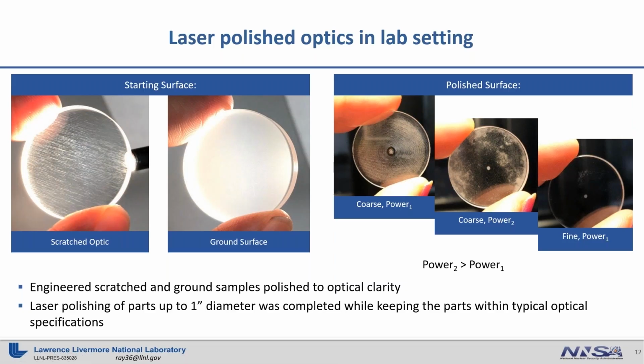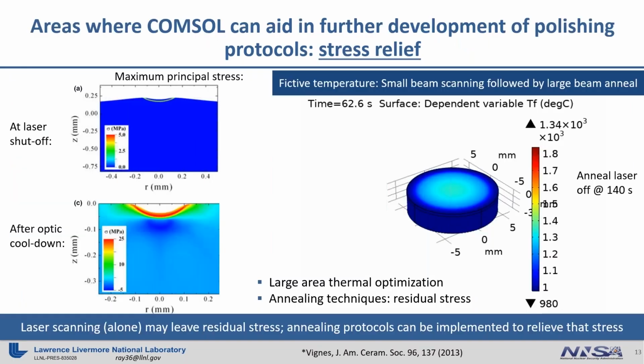So we see with power 1, which we'll just call the low power, there was some polishing. But if we go towards the middle, which is a coarse grind fused silica, but a higher power, there was even more polishing. And now you can see some areas where there's optical transparency. And if we go to a fine grind initial surface with a low power, that optic actually was in typical optical specs. So that was pretty exciting, and we were able to take the results from the model and put it into practice. Where can we go with this model next?